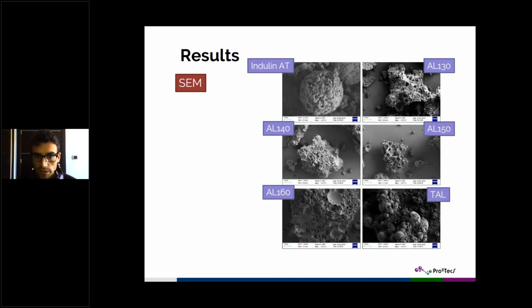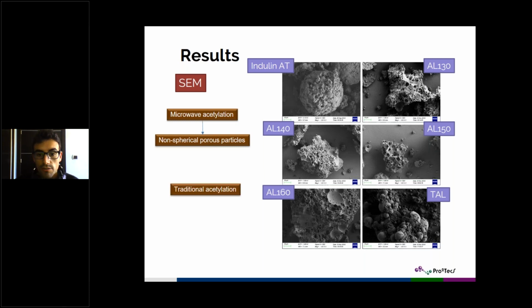So let's now pass to the scanning electron microscopy. As we can see, for the Indulin AT, we get a porous structure with kind of spherical shape, and they are big clusters. But when we pass to the microwave acetylated lignins, we can see that there are huge differences, as those microwave acetylated lignins have a very porous structure and non-spherical shape. While for the traditional acetylated lignin, we have spherical particles with no porosity. So by changing the processing protocol, we can obtain lignins that have very different surface appearance. That's also a really good outcome that we observe here in this study. And that surface difference will have a big influence on the properties of the gels, as we will see.